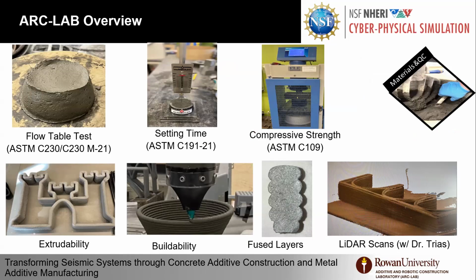So what we do in the lab, as you can see here, if you have this flow in regular concrete, you might not accept it, but for 3D printing, you want to print layer by layer. So we do a lot of tests using flow testing and setting time to identify the window that is valid for printing, a lot of compression testing to verify the material as cast and as printed, and a lot of tests for the extrusion of the material and extrudability, and buildability, where we test the ability of the material to retain its shape without failure.